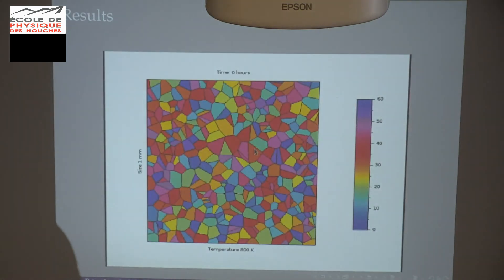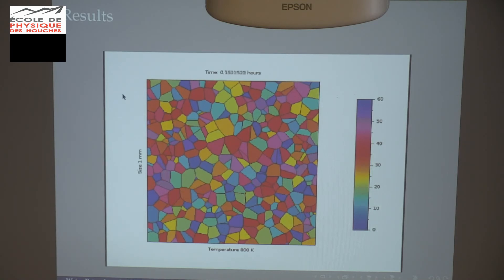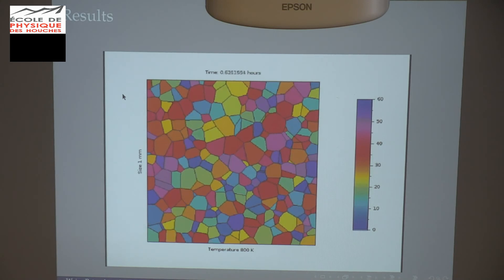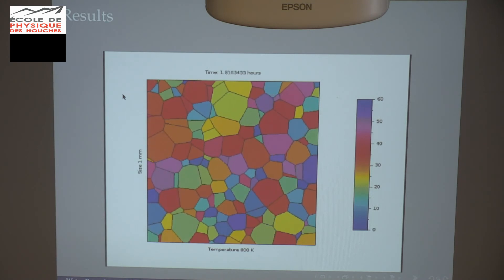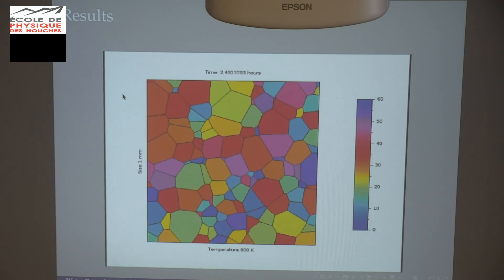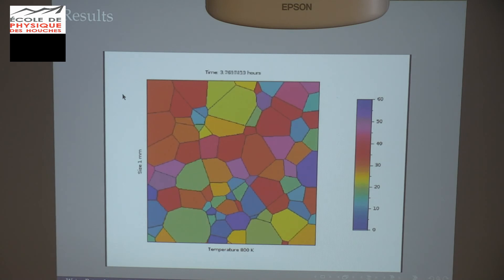Here are some results. We start with some Voronoi tessellation with orientations — since it's a planar hexagonal arrangement, orientations go from zero to sixty degrees because the symmetry is periodic every sixty degrees. You let time evolve, with the mobility calibrated for pure iron from the work of Sinclair and Brechet, which also depends on temperature. You can see the grain growth, and this can be computed very, very quickly.